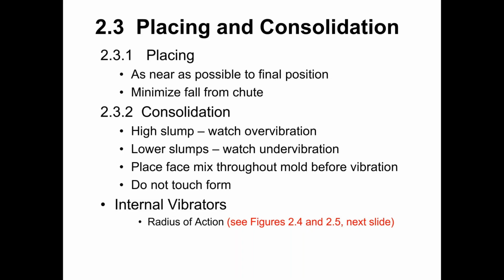that concrete. Whatever method we're using to consolidate the concrete, generally we want to avoid touching the form with our vibrator, unless it is an actual external form vibrator, then obviously the vibrator would be touching the form. But for any other form of vibration, we want to avoid touching the form surface, as it can cause localized amplification of the vibration that can cause segregation in that localized area.